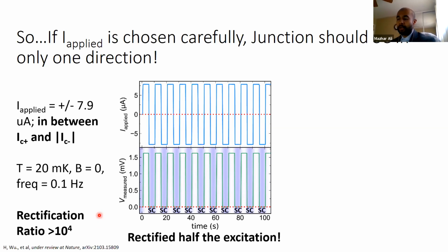So we really are rectifying half of this excitation. So it really is, again, like a diode. It's superconducting in just the one direction when we choose this applied current carefully. Now this is 20 millikelvin, and the rectification ratio is really high because it's superconducting to not superconducting. So it's at least 10 to the 4, basically.